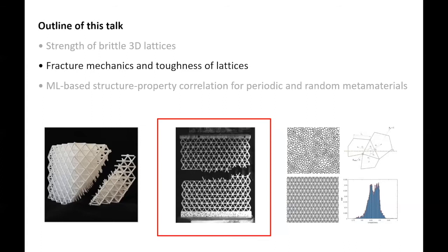That is a good point. The answer is we didn't know beforehand. I was hoping it would not come down to that, because we didn't want to characterize the material this year and have to do all of this. Now, what we found is that... But you're saying that for this material, but if I change my material and look at the same geometry and choose a material that is very weak in shear, then it could play a role, in certain topologies, not in all of them. Because again, the junction can have some type of stress concentration, but that does not mean that the failure is going to be there. It's a very delicate thing.